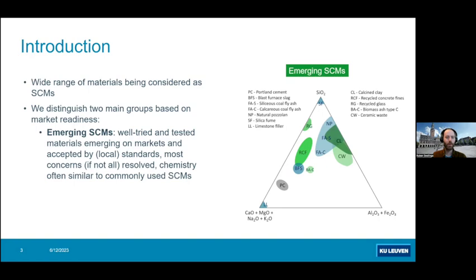But what is striking, if we look at the chemistry of those materials that we classify as emerging, is that they're fairly close still to the chemistries of the materials we know fairly well, blast furnace slag, fly ashes, and so on. For instance, calcined clays are fairly close in composition to fly ashes, while obviously recycled concrete fines are somewhere in between quartz and Portland cement, or silica and Portland cement. So they all plot in this sort of upper part. So I'm going to use the laser pointer. They'll all plot in this upper part of the ternary diagram.